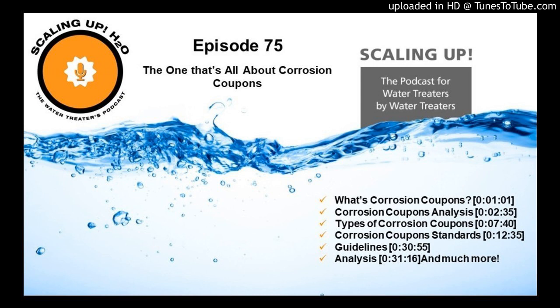So we get all the organics off by putting a cleaner into the flask that we're using. We put that into an ultrasonic cleaner, and we add a certain amount of heat to it based on that standard for a certain amount of time based on that standard. And then we rinse those off, and then we put those coupons, now that we've got all the organics off of them, in an inhibited acid. What that inhibited acid is meant to do is to clean off all the corrosion byproducts from the exposure period that took place on that coupon. So now we've removed all the byproducts and we just have bare metal on those coupons.